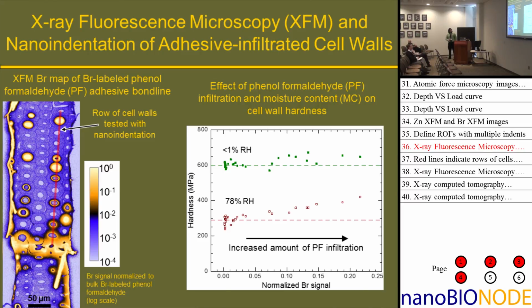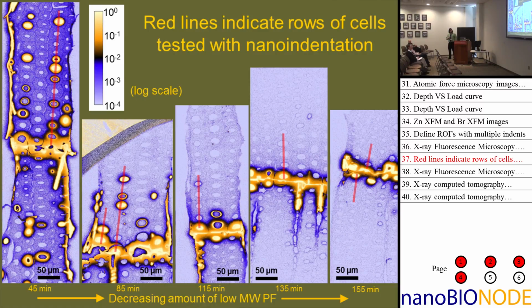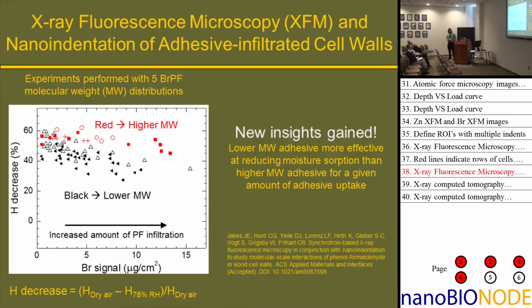We also did experiments with a variety of different molecular weights. You can see that these low molecular weight adhesives are less viscous and they flow far into the wood cell wall, into the wood structure, whereas these higher molecular weight adhesives stay very close to the cell wall. So really the most interesting thing that came out of this study was that there was a difference between the lower molecular weight adhesives and the higher molecular weight adhesives. This difference shows that the lower molecular weight adhesive, for a given amount of adhesive uptake, was more effective at preventing the moisture-induced softening in the wood cell wall.